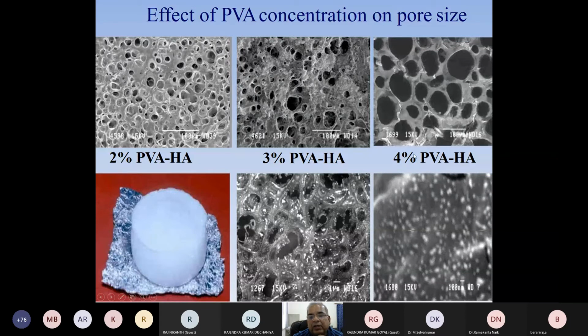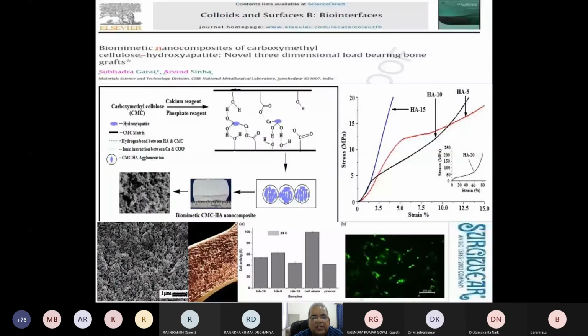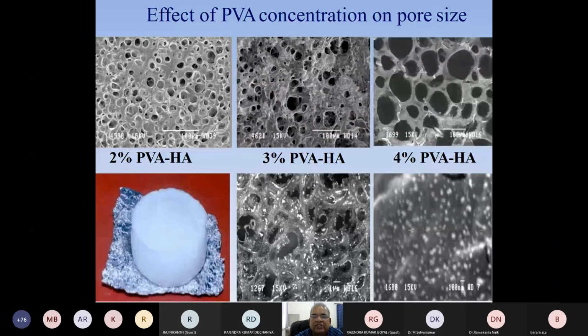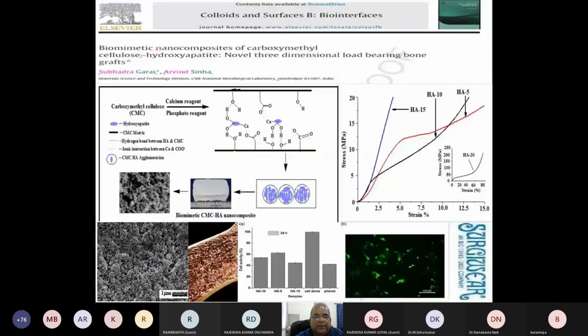We produced it with different polymer concentrations, carried out scanning electron microscopy, and noticed that the pore size changes with polymer concentration. When we increased the magnification, we found that these polymer walls are highly mineralized with hydroxyapatite nanoparticles. You can look here, and they are around 80 to 100 nanometer in size. The problem was that the mechanical strength was not good, so we cannot use it for load-bearing implant application. For non-load bearing, it's fine.